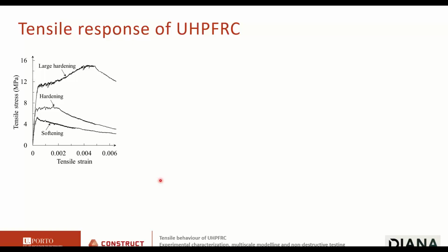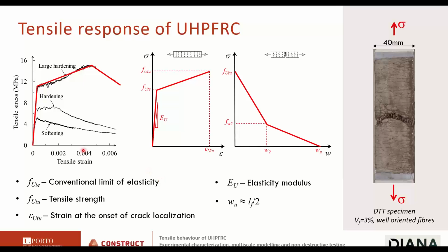The tensile response of UHPFRC is well illustrated here in this plot. All these curves have been obtained with the same cementitious matrix, same types of fibers, but different fiber contents and different fiber orientations. Typically, if you want to do a structural analysis or a finite element analysis, you can model this behavior by a bilinear law up to peak stress. It's sufficiently accurate.